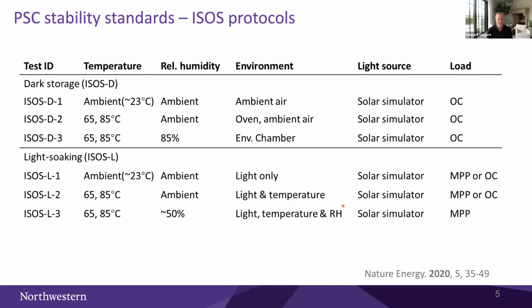So obviously performance is important and stability is just as important. And so this is an area that's also been seeing a lot of focus and a lot of progress. I'll be making reference to various ISOS protocols and standards today, including the dark storage and also under illumination. I think it's fair to say that maybe my favorite is the ISOS-L-3, which is being reported at the maximum power point and at 50% relative humidity, and typically at either 65 or 85 degrees C. You'll see that temperature called out.